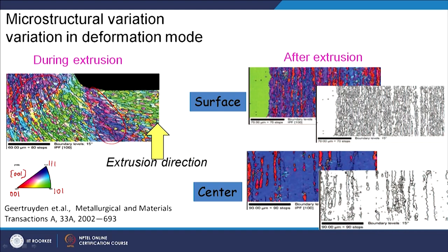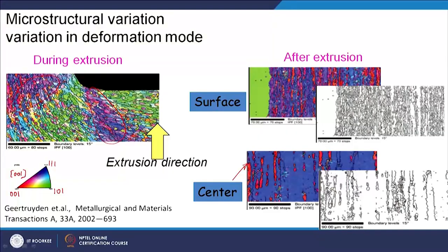Similarly, another very nice example of variation in the microstructure because of the variation in the strain in the extruded billet. So, this particular microstructure is at the center of the billet and this one is at the surface. So, you can see that in the center you have a different type of grains, only blue and red ones.